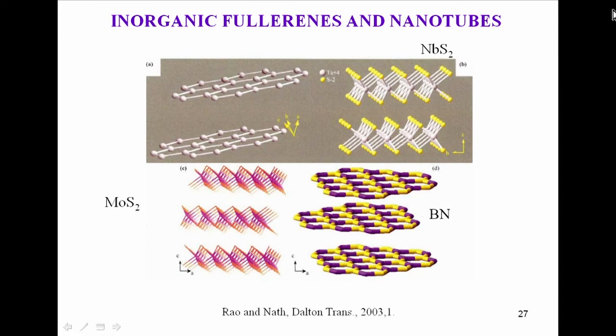Well, here I want to leave carbon. You see, many of us think carbon nanotubes, Fullerene, they all have to have carbon. But many years ago in Israel, in Weizmann Institute, my friend Tenne showed that Fullerenes, even though they were first made of carbon, can be made of inorganic layered materials, which are also just like graphite. See, Fullerene is derived from graphite by arc evaporation of graphite. Why not make similar layered materials in inorganic? So molybdenum sulfide, boron nitride, they all have structures similar to graphite.